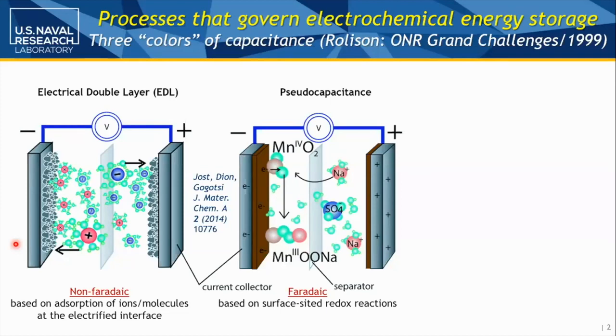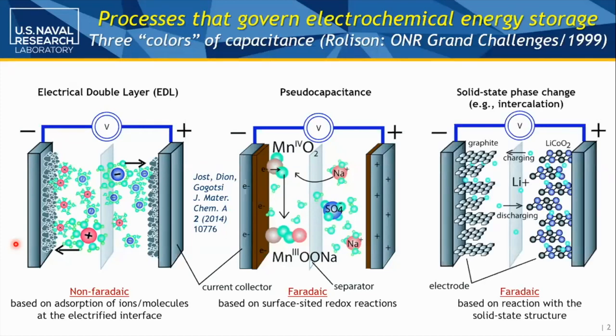So the pseudocapacitance mechanism was recognized as another way to store energy. And then, of course, the classic, if you will, lithium ion battery, where not only is the Faradaic reaction occurring, but ions have to insert into crystallographic orientations to create the stored electron ionic charge in the system. So you can consider these three, if you will, colors of capacity. That way we can store energy in a two electrode or a two terminal device.